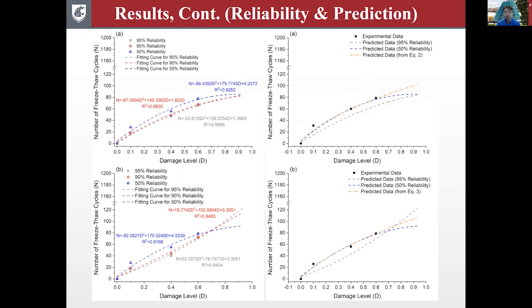So by employing a 3-parameter Weibull distribution model, we can develop equations for predicting the number of cycles that concrete specimen can still stand with a known damage level with different reliability levels. Here we selected 3 different reliability levels with 50%, 90%, and 95%. As we can see here, with the increase of the reliability level, the prediction of the number of remaining cycles that concrete can still withstand becomes smaller, which means that with a higher reliability, the prediction will become more conservative.